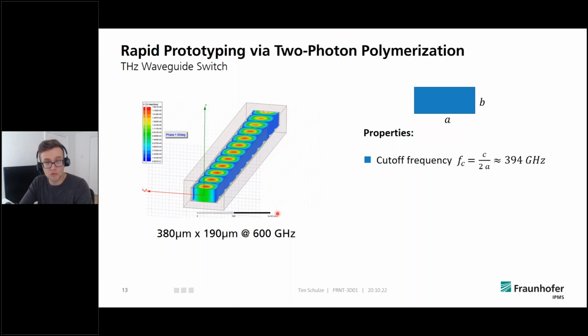So I've been working with hollow rectangular waveguides for terahertz radiation, and those waveguides are indicated here. So it's just a tube with a rectangular profile, metallic sidewalls, and terahertz radiation can propagate through it. In this case, for instance, it's at 600 gigahertz. And the issue with those waveguides is that they have a specific cutoff frequency. So waves are only able to propagate within this tube if the propagating frequency is higher than the cutoff frequency. And for instance, for a waveguide with this dimension, the cutoff frequency is only determined by the width of the waveguide, and this is approximately 400 gigahertz.